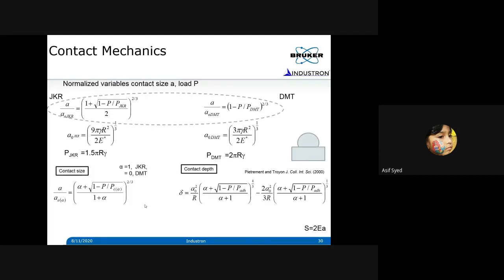Now there are three different methods that we can use. One is the way that I mentioned, the optical method, where you can see the size of the contact. In my next slide, I will show you some videos so you get a clear understanding of what I mean. You measure the size of the contact through an optical microscope, and once you know the size of the contact and the force you apply, you use this formulation to calculate the modulus of the material. That is a pure optical technique. The other way is to measure the depth of indent from the load displacement curve, the way I've shown you before, and convert this contact size into depth, and then use this formulation to measure the properties.